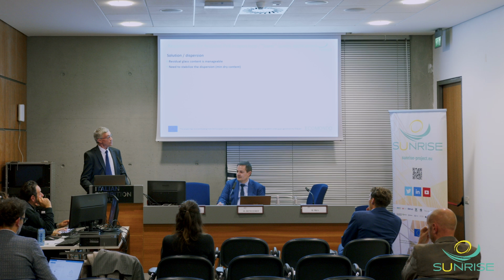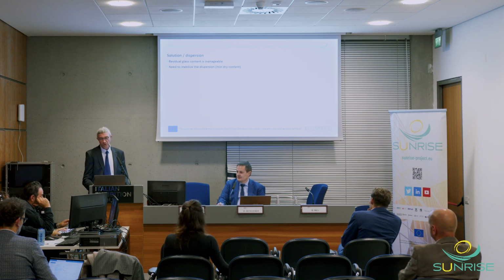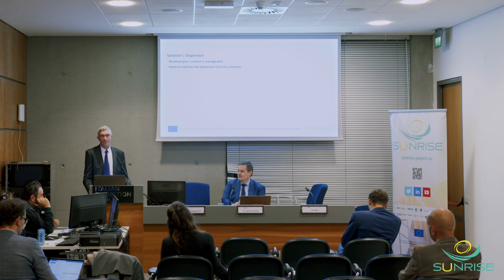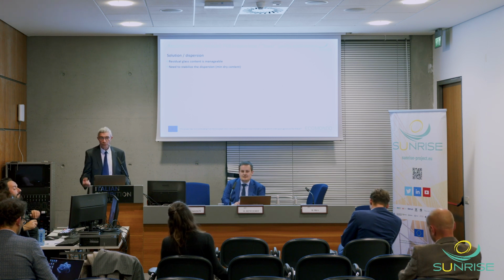So the requirements for open loop, of course, if you work with the solution and dispersion, you have a manageable residual content of glass, because in a solution you have a sedimentation of glass, so it's a good separation. But you need to stabilize the dispersion to have a minimum dry content. In the trials we did within the Sunrise project, we had some problems with that. It was not able to get a stable dispersion. You got also the sedimentation of the PVB.